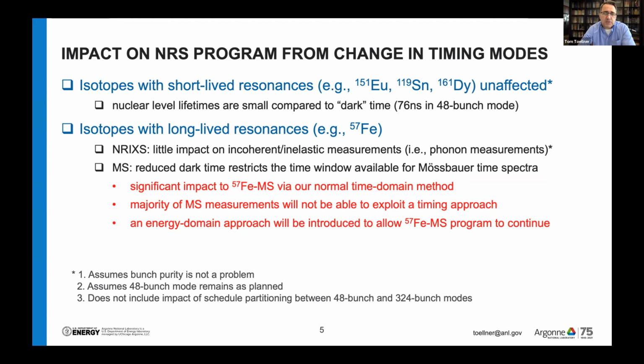The 76 nanosecond dark time, once you subtract out time loss because of the timing electronics and potential bunch purity issues, that 76 nanoseconds could easily be cut in half down to something like a 30, 40 nanosecond time window, which is mostly unacceptable for almost all iron-based Mössbauer spectroscopy measurements. So we'll introduce a new energy domain approach to accommodate and allow that program to continue.